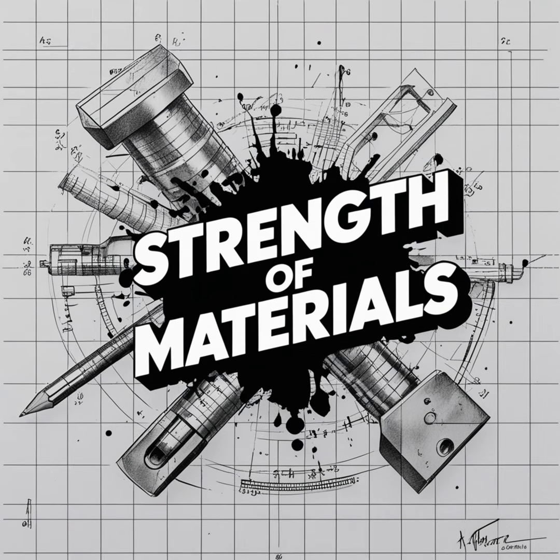1 meter thick. You'd need a testing machine the size of a building just to pull it apart. It's physically impossible and absurdly expensive. Exactly. The industry was hitting a wall, but with the J integral, because J can handle large-scale yielding without breaking a sweat. Exactly. The specimen size requirements for a J test are exponentially less severe. You can take a highly ductile steel, machine a small, deeply cracked, compact tension specimen, maybe just 1 inch thick, put it in a standard lab machine, measure the critical J value at failure, and then use the mathematical equivalence to back-calculate what the equivalent linear toughness value would be.